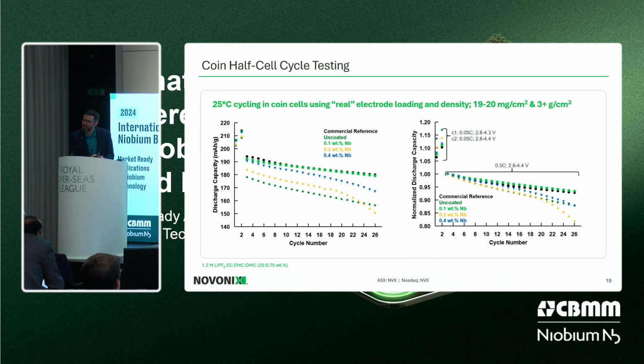I find it very interesting that you only need a small amount of niobium to make a huge improvement, but there is a limit, and that limit is apparently 0.1. When you go beyond 0.1 weight percent niobium oxide on the surface, you end up having too much material, which actually decreases your capacity retention. But we're going to continue on with this project and continue into full cells shortly. So right now it's just coin cells, but we'll get there.